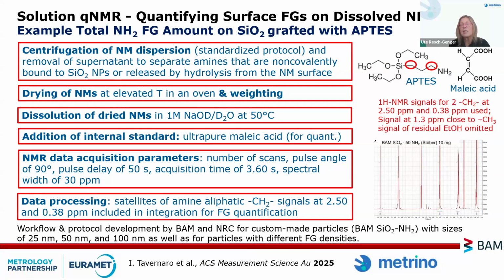In this case, we had to dissolve the particles because otherwise, well, you don't see a signal of the ligands on the particles. The particles are too large. You have too broad signals. They don't show up. So here I showed the signals we are looking into when you have aminated particles. We used maleic acid, showing signals at different NMR shifts compared to what you wanted to quantify.